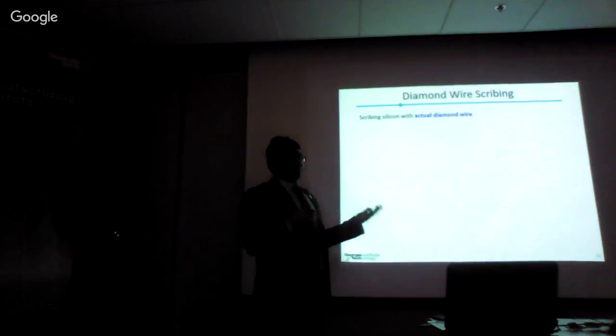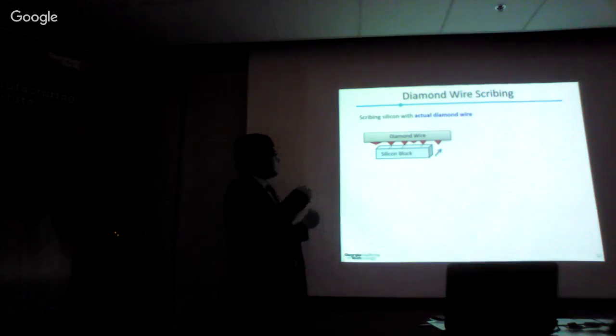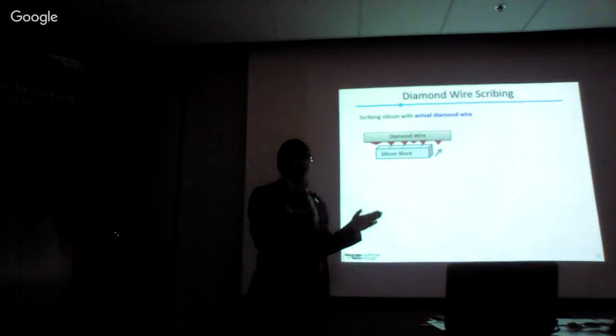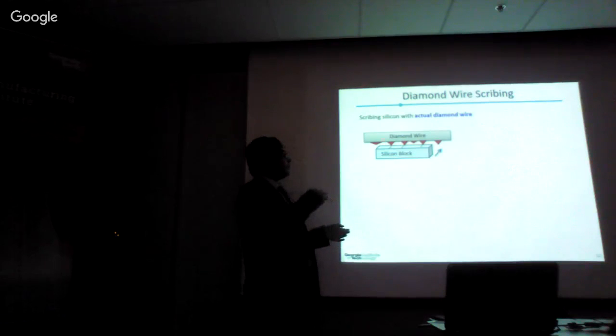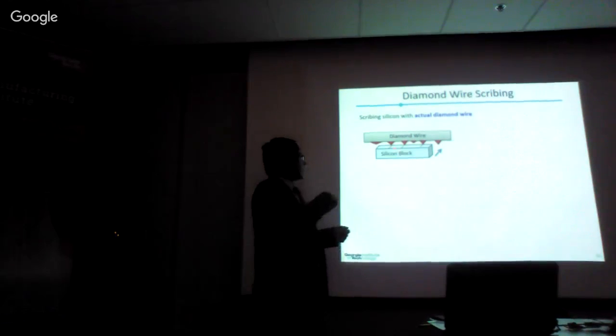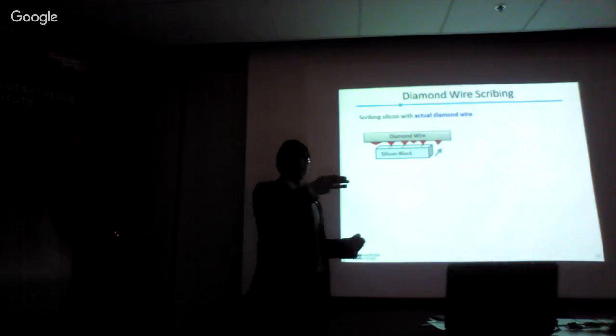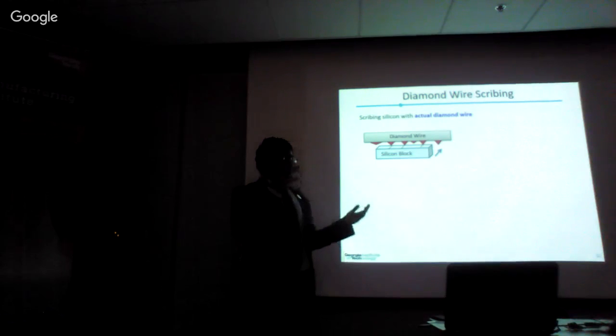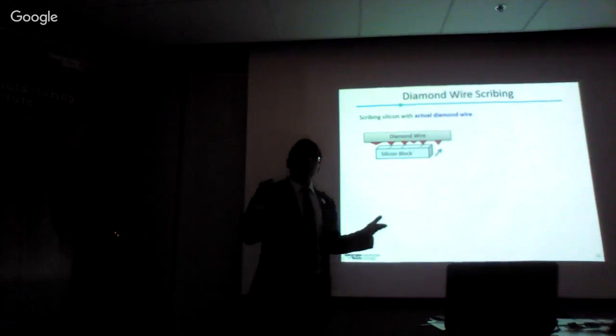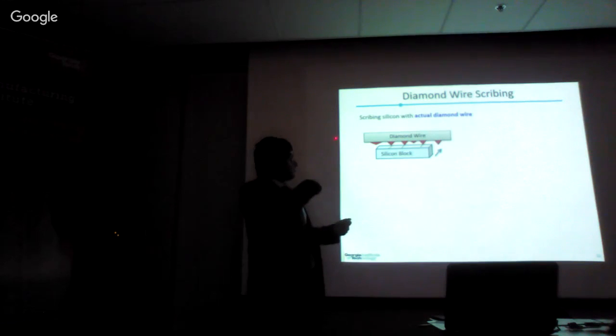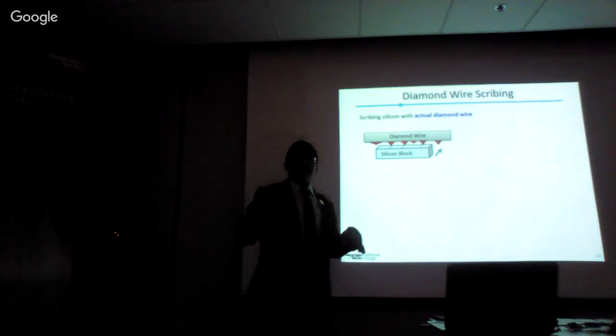So when we scribe silicon with the actual diamond wire, we have to note in this experiment that we have to find the effect of each abrasive shape. Hence, we are holding a diamond wire with a fixture and translating the silicon block perpendicular to the wire. This is a difference from the actual wire sawing process, where the silicon is being cut by the abrasive by translating the diamond wire parallel to the length of the wire. But in this experiment, we are to find the effect of each abrasive shape.